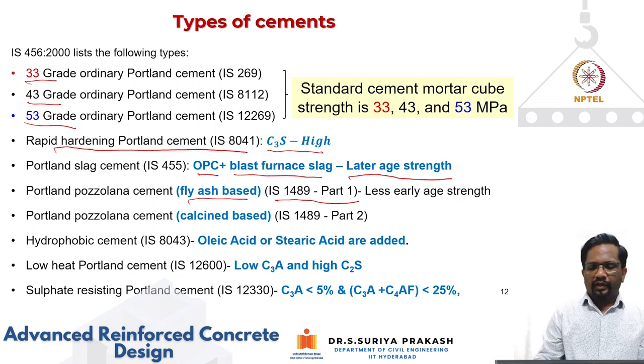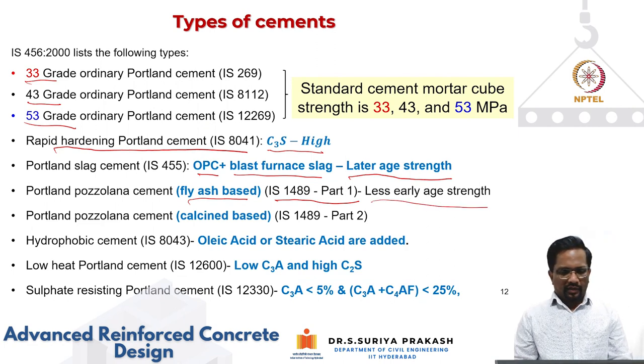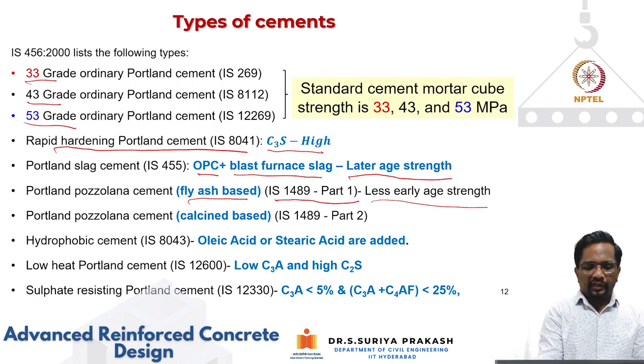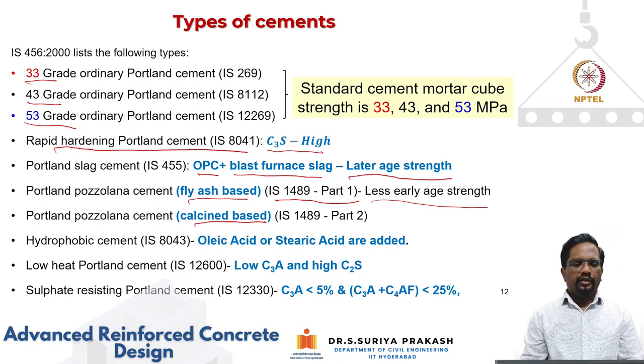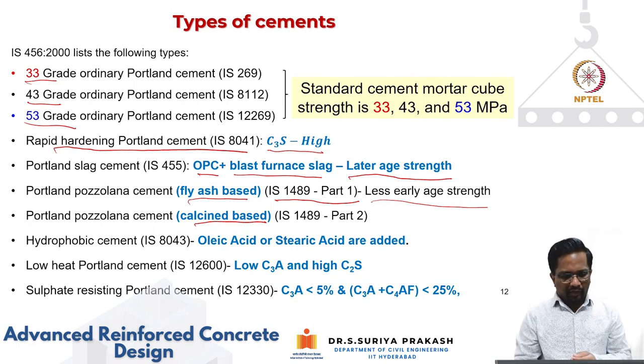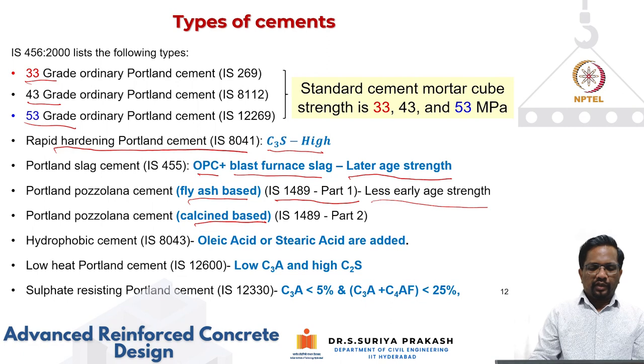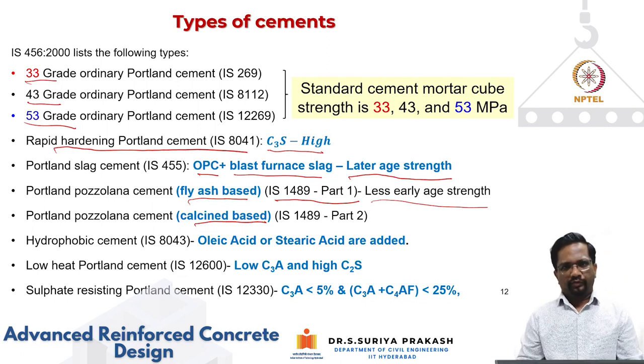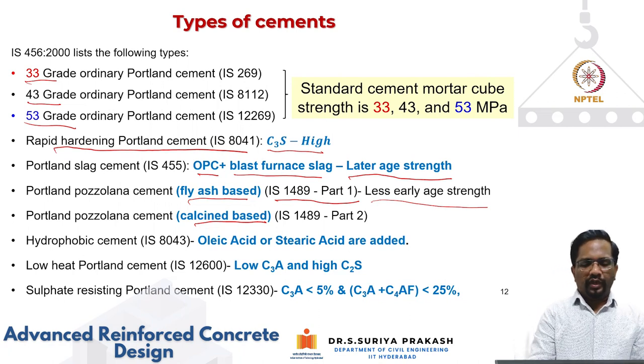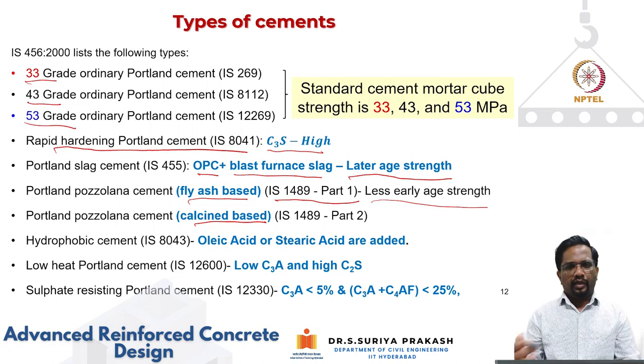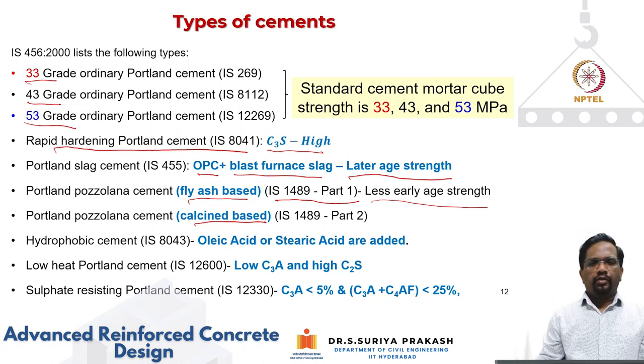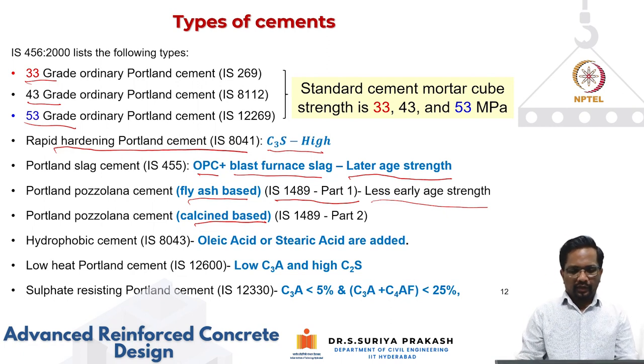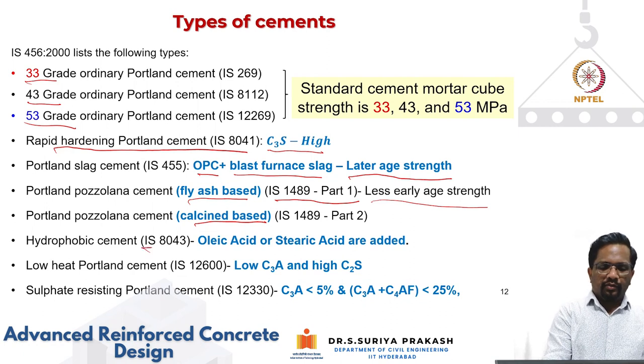on fly ash. So fly ash is added, and so again you get less early age strength, but high strength at a later stage. Then we also have Portland pozzolana cement, which is calcined clay based. The specification for this cement is given in IS 1489 Part 2. Sometimes for certain specific applications, we also want hydrophobic cement. For example, if you want to store cement for construction exposed to moisture, then oleic or stearic acid is added in the manufacturing process, which gives the hydrophobic property to the cement, so it is not going to set while you are storing the material. This is also available, and should conform to IS 8043.